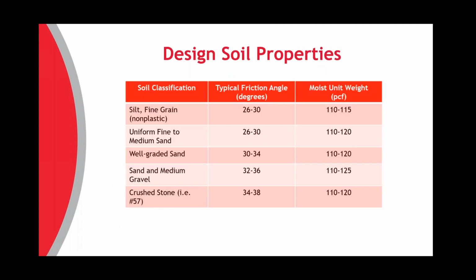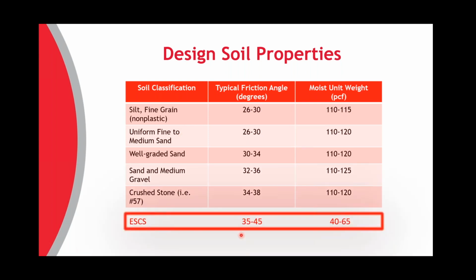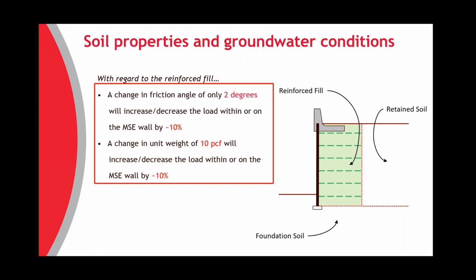If you recall this slide from earlier that showed the properties, the shear strengths and the unit weights of typical aggregate materials, the ESCS, again, is higher in shear strength generally, and about half the unit weight. And if you recall this slide from earlier, a change in friction angle of 2 degrees increases or decreases the load by 10%. Unit weight, similarly, 10 PCF will increase or decrease the load by 10%, which can increase or decrease your soil reinforcement requirements behind the wall.